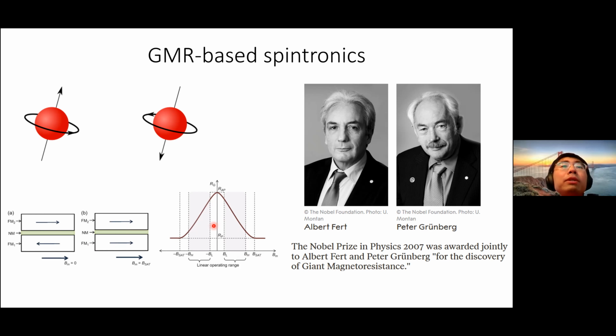So in this case, by measuring the electrical resistance in the system, you can effectively measure the spin polarization of this bottom region, if we know that the top region has the same spin polarization. So in this case, we can read out the information stored in the spin by electronic signals.